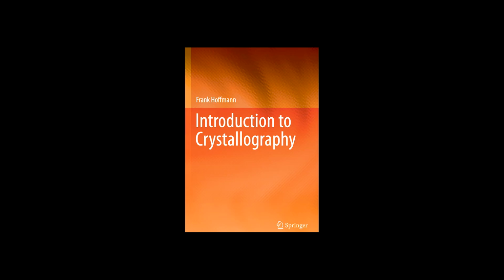And is this golden ratio just theoretical, or does it show up physically in the quasicrystals themselves? Oh, it shows up physically, absolutely. For one thing, the ratio of the edge lengths of the two rhombi used in the 2D Penrose tiling is exactly the golden ratio. More strikingly, when you manage to grow single crystals of quasicrystalline alloys large enough to see their external shape, their morphology, they often grow into highly geometric shapes that exhibit the forbidden five-fold symmetry externally. Common shapes are the icosahedron, a solid with 20 identical equilateral triangular faces, or the regular pentagonal dodecahedron, a solid with 12 identical regular pentagonal faces. Both shapes intimately related to five-fold symmetry.